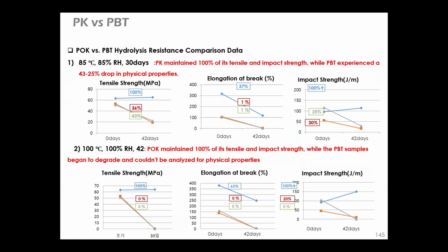Polyketone and PBT for the hydrolysis resistant comparison data. So high temperature, high moisture environment. So 85 C, 85% relative humidity, 30 days, and 100 C, 100% relative humidity for 42 days. The blue color of polyketone always shows more stable than PBT, which is gray and orange color. So again, the retention rate for the long time, polyketone shows always more stable than PBT.